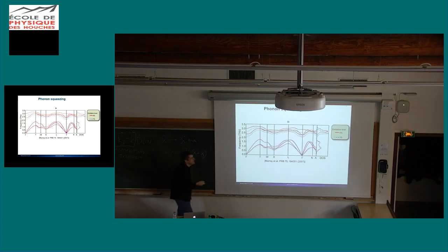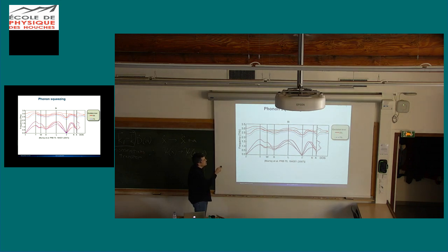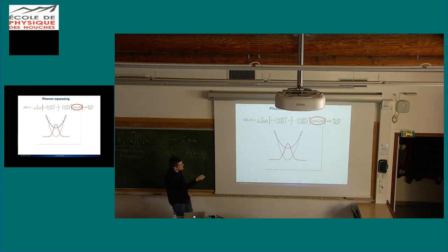So in bismuth, it turns out that if you strongly electronically excite the system, you actually do have a change of the frequencies of at least some of the modes. So this is a calculation at two different electronic excitation levels. Red is the ground state, and the dashed blue is with 1% of the electrons from one band promoted to the conduction band. You see changes depending on where you are looking in the dispersion. The optical phonons are more strongly influenced, but the acoustic modes near the zone edge are also influenced. Generally, it either doesn't change much at all or it decreases the frequency. So that's exactly the kind of thing that I showed here, where you have this change.